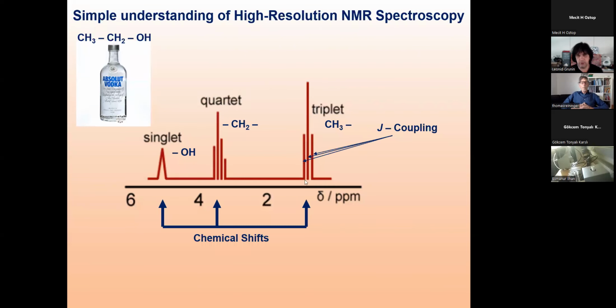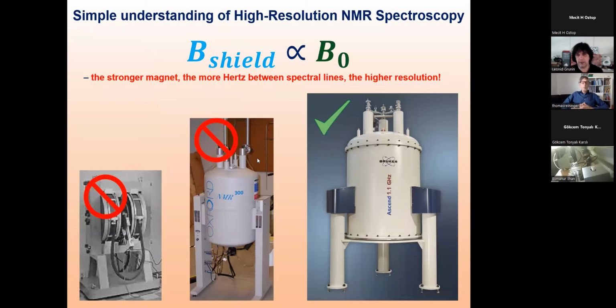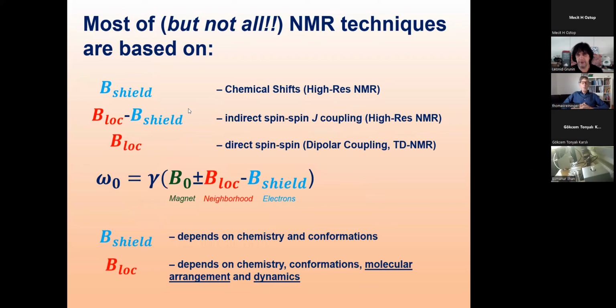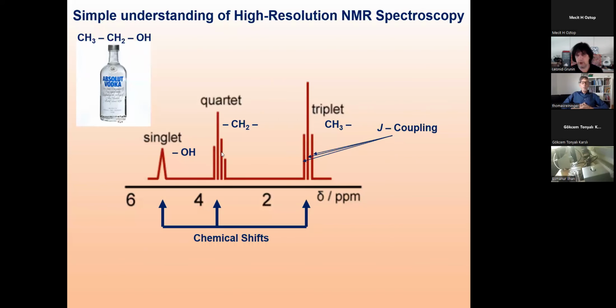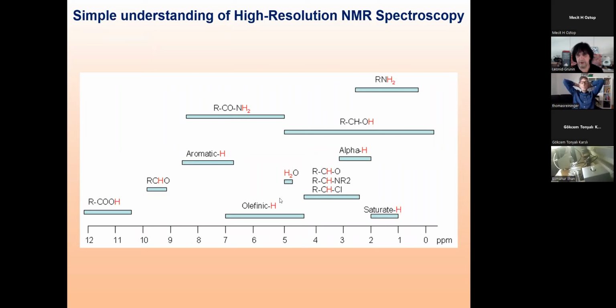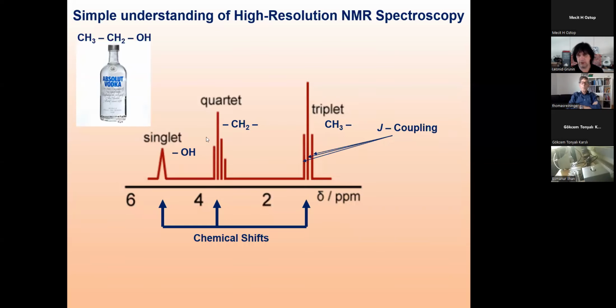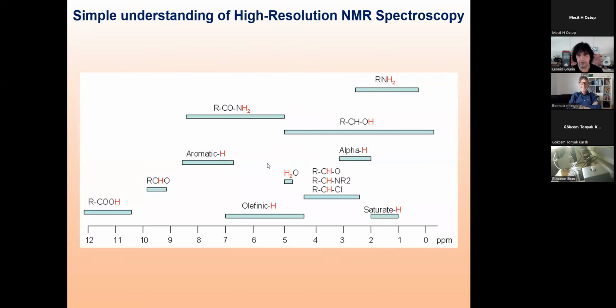But to simply understand it, if you take ethanol and put it inside the NMR machine, you will get this splitting. This is what we call the shielding field. Then you will have 3 big lines, and these lines will have fine structure depending on the indirect spin-spin coupling. This is the basis of high resolution NMR. You get the spectra, you process the spectra, and sometimes you make multi-dimensional spectra, and you get extremely important information. These ranges of chemical shifts depend on the chemical structure of electron clouds. For protons, it's within ppm, parts per million, and there is already a measured library, so looking at the spectrum, you can tell without drinking that this is pure ethanol or this is not pure ethanol.